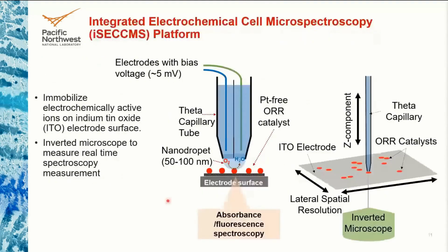How we combined it is basically we use the SECCM platform on a HEKA platform that we purchased, and instead of using an opaque electrode, we used an ITO electrode, and we constructed an inverted microscopy setup under the surface, so that we can focus the objective lens directly on the tip end.